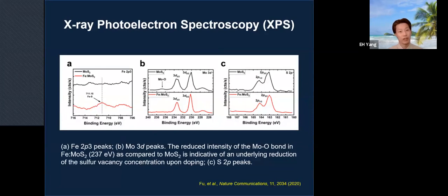We use X-ray photoelectron spectroscopy. This was done at ASRC, and so figure A shows iron 2p3 peaks, and B and C show molybdenum and sulfur peaks. So you can clearly see the existence of iron elements in this material, right?